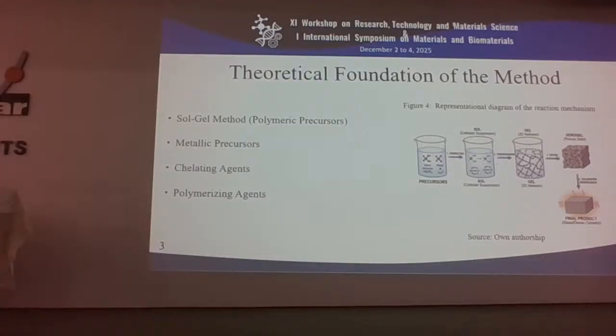Now, the theoretical explanation of the method. In the synthesis, I utilized the sol-gel method, which is sometimes called the polymeric precursors method. Here you have the representation diagram of the reaction mechanism. The first thing you need to do is make a solution with your metallic precursors, and the choice of them depends on what properties you want the output to have. After you make the solution, you add the chelating agent, whose function is to form complexes to avoid precipitation. After that, you add the polymerizing agent to form a polymeric matrix with the complex to facilitate the formation of the reticulated material. Then you lead your sample to drying to remove residual solvents, and after that to calcination, where you have the densification and crystallization of the product.